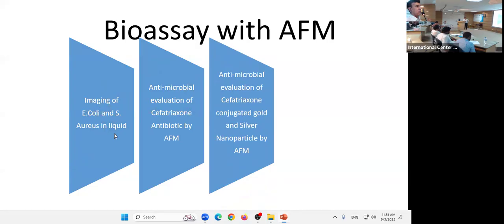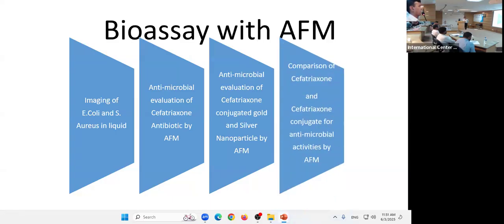This was a bit old, but later on we also did this experiment in air, because with liquid it was much more difficult. The result I'm showing here is not in liquid, but in air. This is the antimicrobial evaluation of ceftriaxone conjugated with gold and silver nanoparticles, a comparison of ceftriaxone and ceftriaxone-conjugated gold nanoparticles.